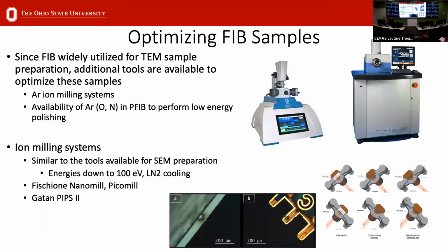There are other techniques for optimizing FIB samples. There are systems available for argon ion milling your FIB samples. The advantage of this is that you can then do those low energy milling steps below 1 keV, down to 100 eV, to progressively remove damage layers. Typically with argon systems, you could also have liquid nitrogen available if you need to use that to remove damage. The NanoMill is a system that we have here that's available for TEM sample preparation.